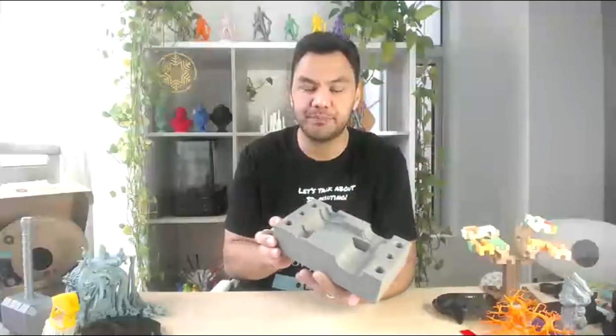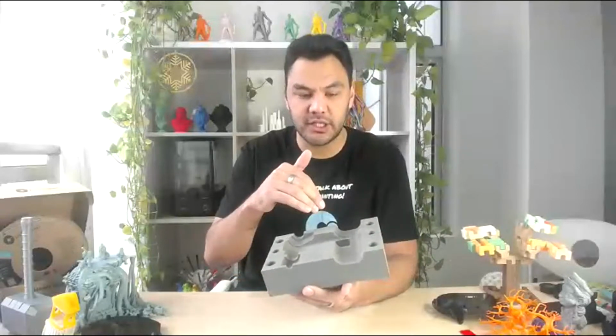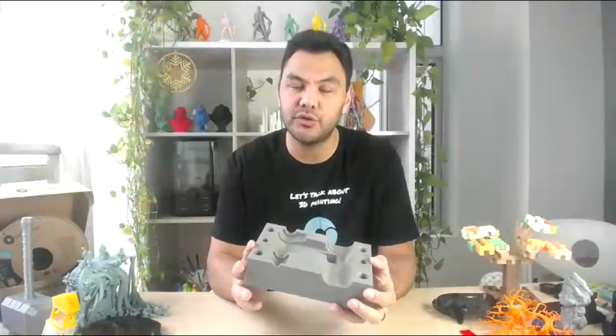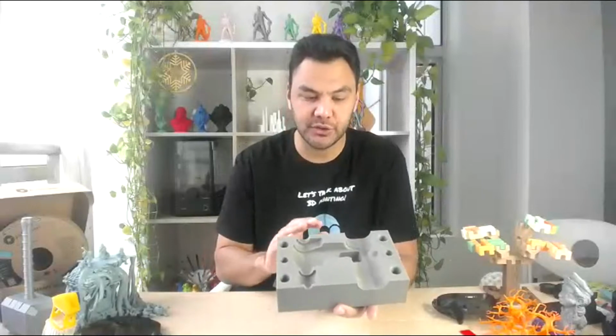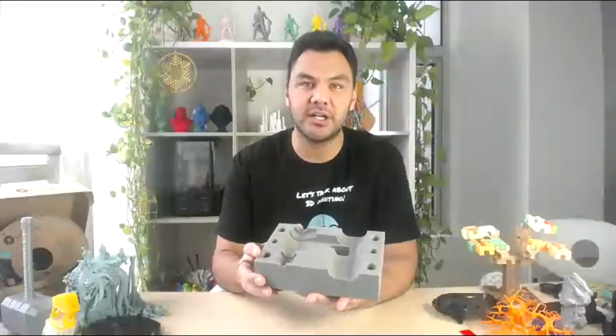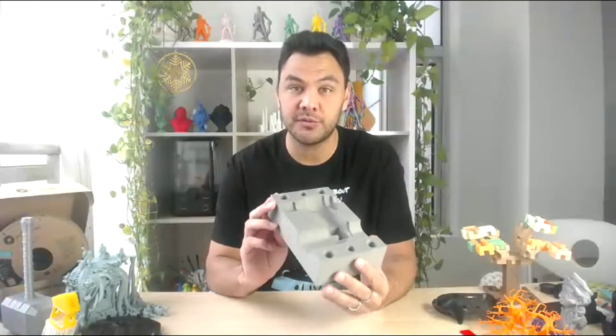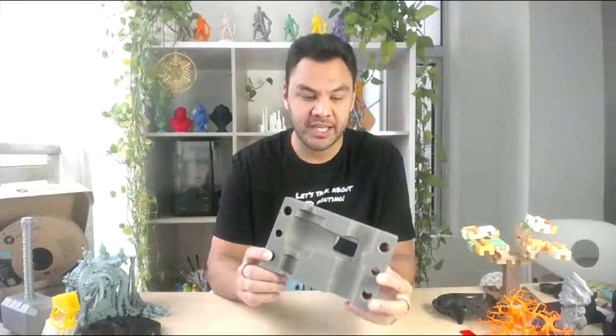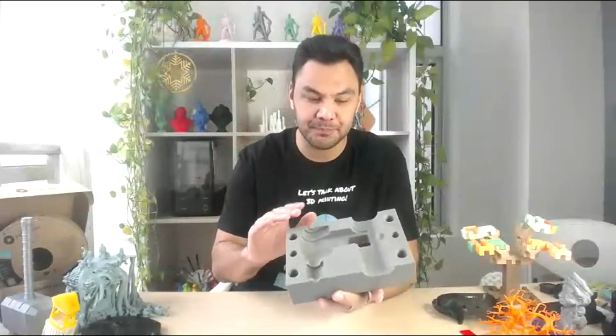So if you stay below 50 degrees for your bed temperature or overall chamber temperature, then you won't have any warping issue. For the nozzle temperature, you can go 280 to 300. So you will need a all metal hot end for printing with GF. And please remember to use abrasive resistant nozzle. And I would also recommend to use it for the drive gear for the extruder if you use it a lot.